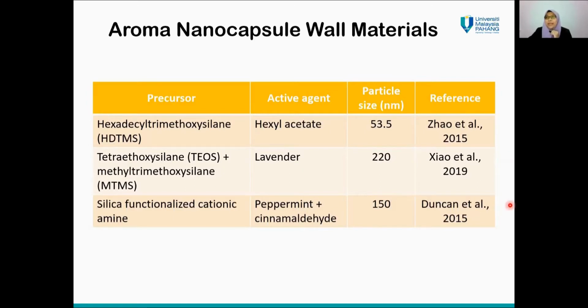In 2015, they functionalized silica nanoparticles with cationic amine and obtained an average diameter of 150 nanometers, self-assembled at the oil-to-water interface to stabilize the mixture of peppermint oil and cinnamaldehyde droplets. Compared to polymeric capsules, these inorganic capsules show excellent mechanical property, morphology, and monodispersity. However, to date, the inorganic capsules have only focused on some special compounds, such as silica. Few properties, including thermal resistance and sustained release properties of the inorganic capsules loaded with aroma, have been reported.